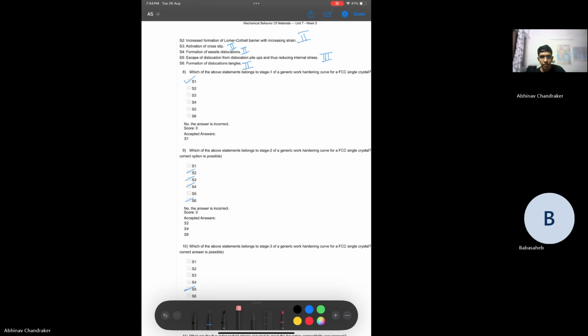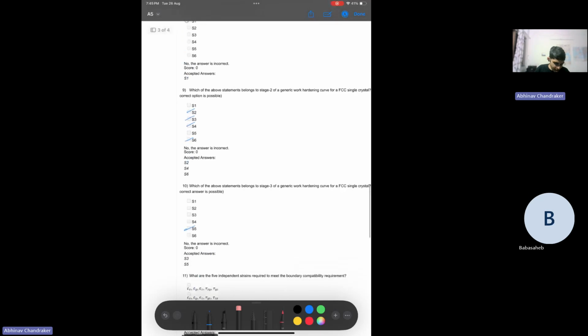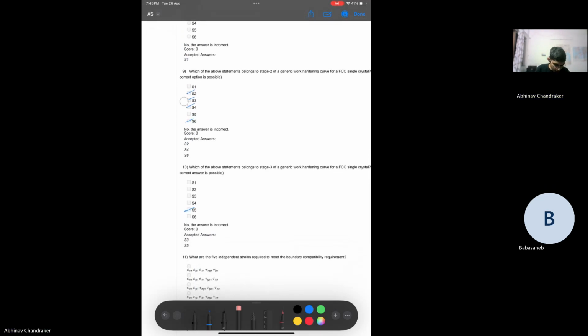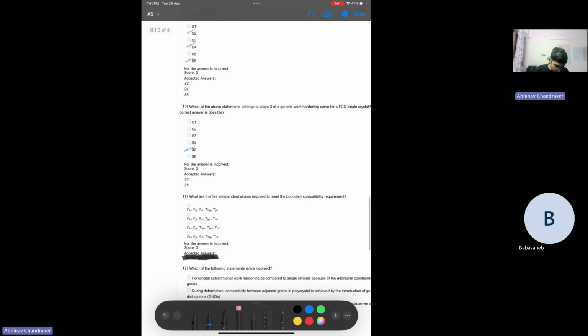Stage 3, both recovery as well as strain hardening occur simultaneously. So one part of recovery is cross slip, but I think cross slip occurs in stage 2 also, but in 3 it becomes even more dominant because that is a way for dislocations to escape. We can say that it occurs in 3. It's a dominant mechanism for 3 and not so much for 2. So fine. Now we are correct as per the answer key.